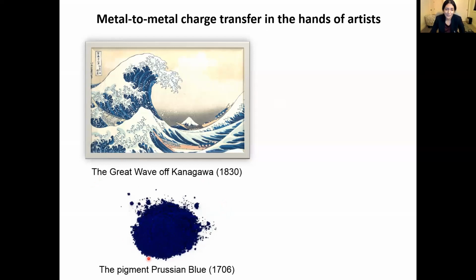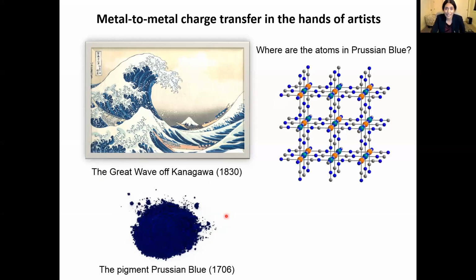So he accidentally made this blue paint, and today we can look at this material much more closely using X-ray diffraction, and we know exactly where all the atoms are, and we find that this has a familiar arrangement of atoms. So we have iron octahedrally coordinated by cyanides, and these cyanides form metal cyanide octahedra that share corners and extend in 3 dimensions. So this is what Prussian blue looks like, but why is it blue?